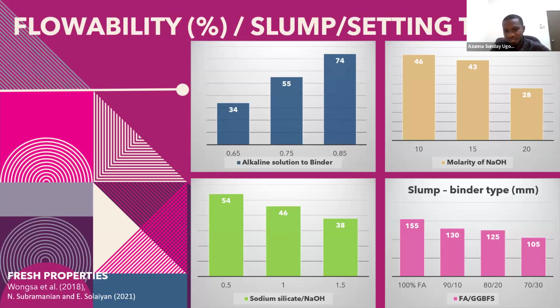So now you can see that your workability reduces with an increase in the ratio of sodium silicate to sodium hydroxide. Now, normally, your sodium silicate is thick. It's a very thick liquid. And your sodium hydroxide is more watery. So if you're increasing the ratio of sodium silicate to sodium hydroxide, it means you're increasing the quantity of sodium silicate in your geopolymer concrete. Now, the viscosity of sodium silicate is way higher than that of water. So it will make your concrete more sticky. The concrete will be sticky. It will not be so watery anymore.